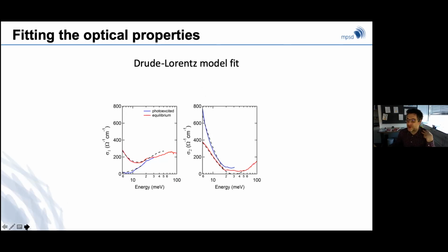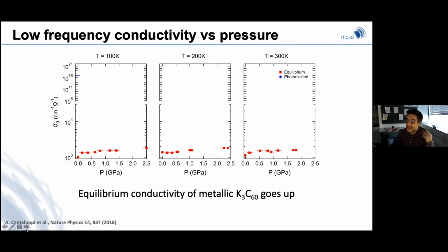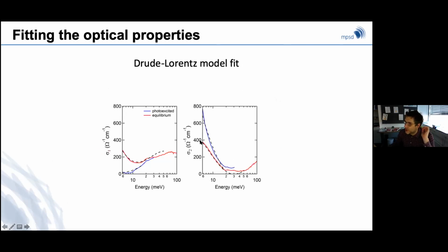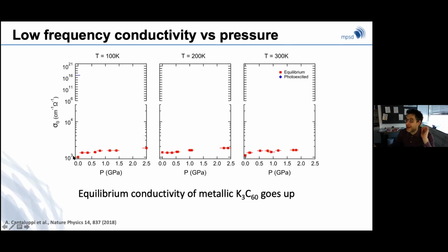which is the inverse of the resistivity, as a function of pressure. Firstly, let's start at high temperatures in the metallic state before I pump the system. At three temperatures, 100 Kelvin, 200 Kelvin, and 300 Kelvin, if you take sigma 0, the extrapolation of sigma of omega measured here in the metal, what you find is what I promised you we were going to find: a metal, the conductivity of which gets better as I apply pressure. So in equilibrium, the metal behaves like a metal, that is, conductivity gets better.